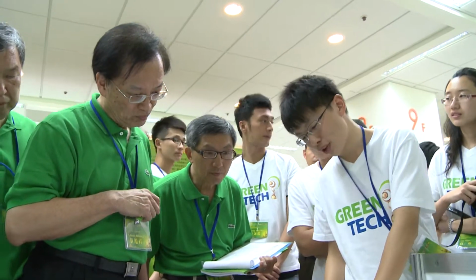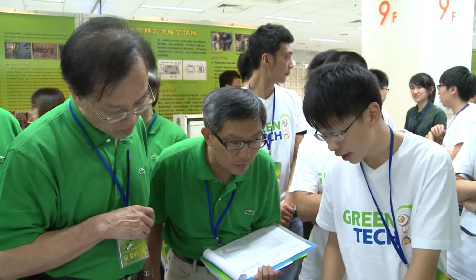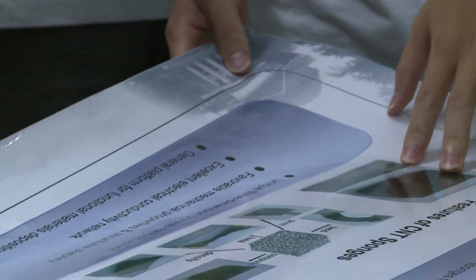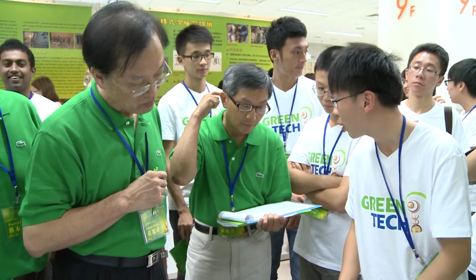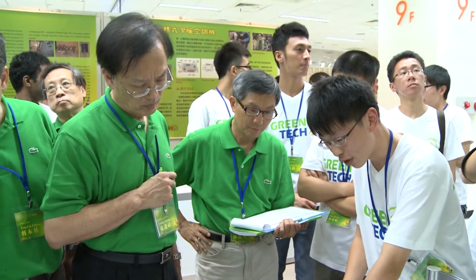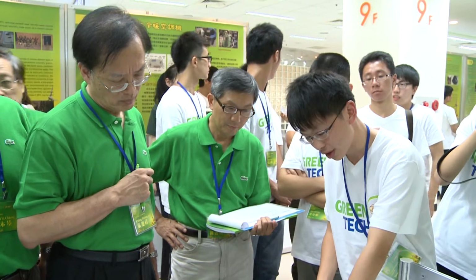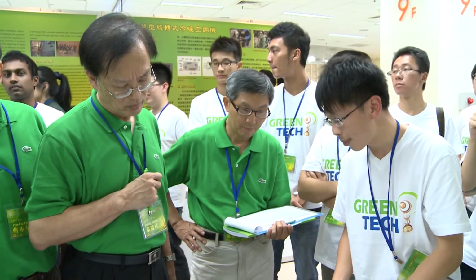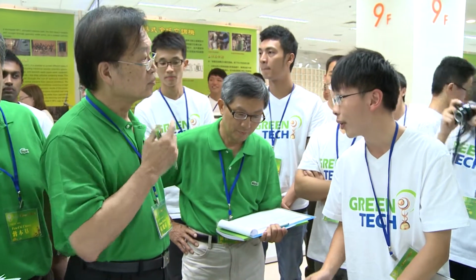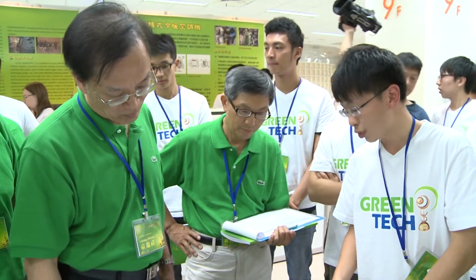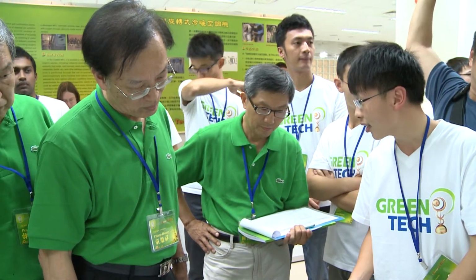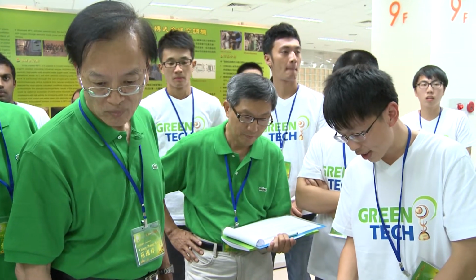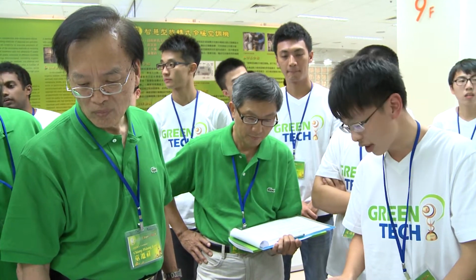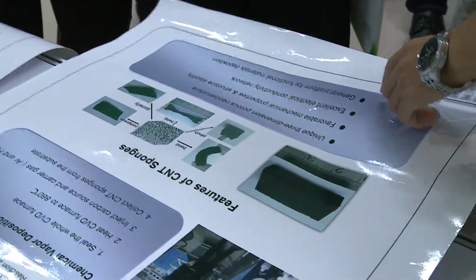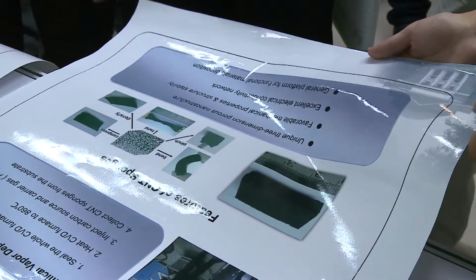And the picture shows a block of CNT sponge. It has a unique three-dimensional, well-controlled porous nanostructure. Another enormous advantage is that the CNT sponges have excellent mechanical properties and structural stability. We can see from the picture that no matter how we handle the CNT sponges, they keep their stability, and they are very compressible and flexible. The CNT sponges also have excellent electrical conductivity, which favors fast charge transport. Besides, CNT sponges have a relatively high surface area, and based on such properties, they provide a general platform for functional materials composition.